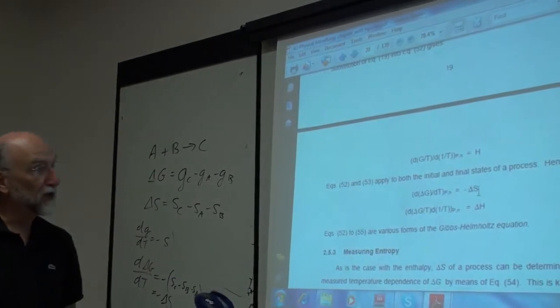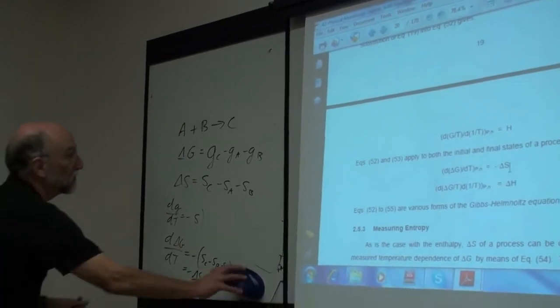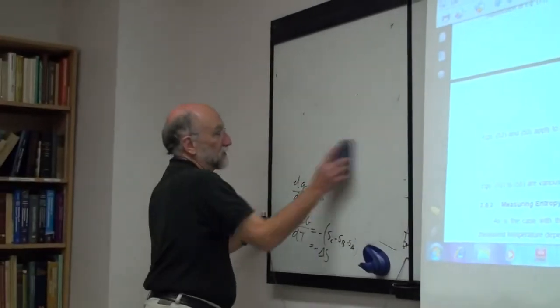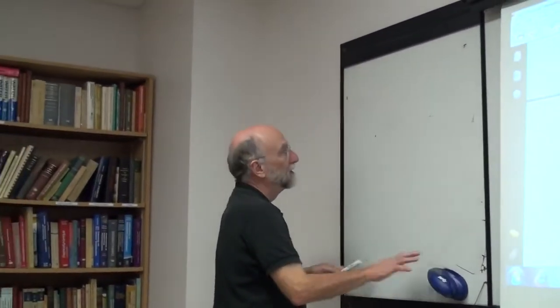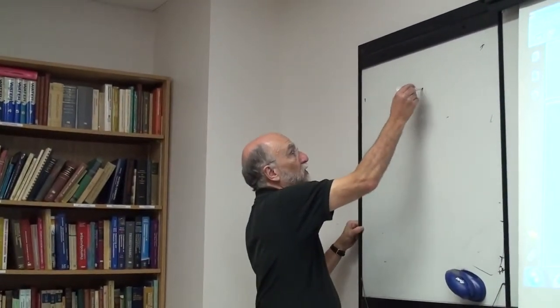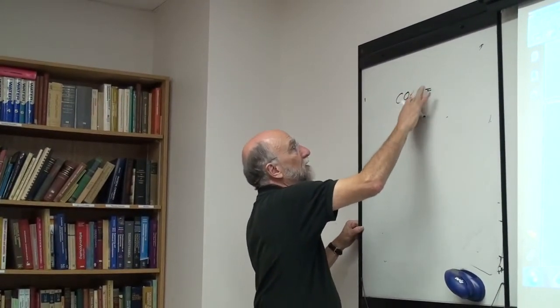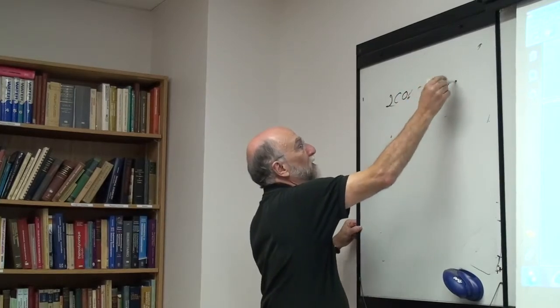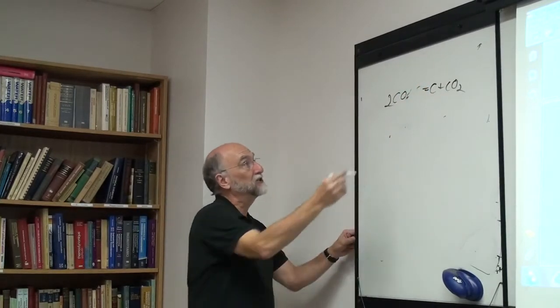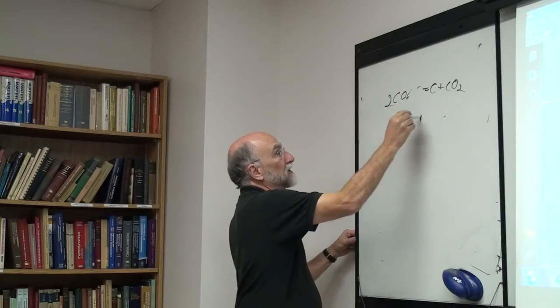It's the same thing if you plot delta G over T versus 1 over T. So this is simply, say I have the reaction, CO plus carbon, 2CO equals carbon plus CO2, for example. I measure delta G. Delta G is minus RT log K.